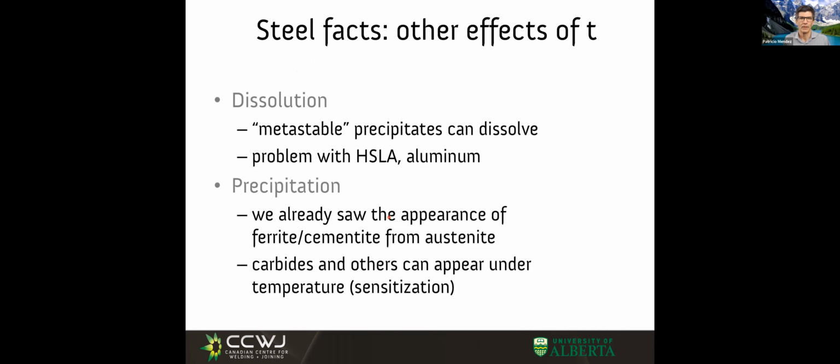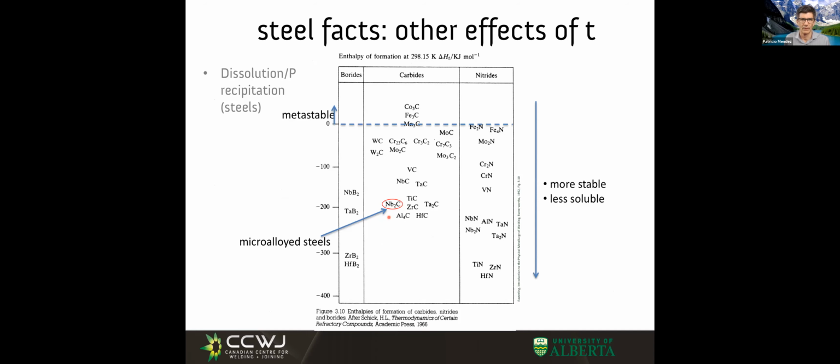For example, in stainless steels, you want them to be austenitic, but if they are hot for too long, for example because you preheated a stainless steel or you use too high of a heat input, it might precipitate chromium carbides. And the chromium, if it is in a carbide, will not help your steel be stainless, and you ruin the stainless properties, and you ruin the toughness too.